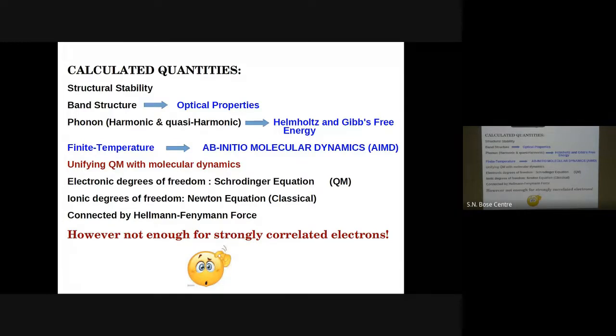Of course, yesterday the GW method was described, which is a much more accurate and correct way of looking at optical properties, because, as mentioned and stressed, you should be clear in your head that density functional theory, being a density-based theory, doesn't have a concept of electrons as particles. That concept it doesn't have. So the eigenvalues of the band structure, you can't actually interpret as the energy of some quasi-particle. We do interpret the DFT-calculated band structure, but if you are a purist, you really shouldn't do it.